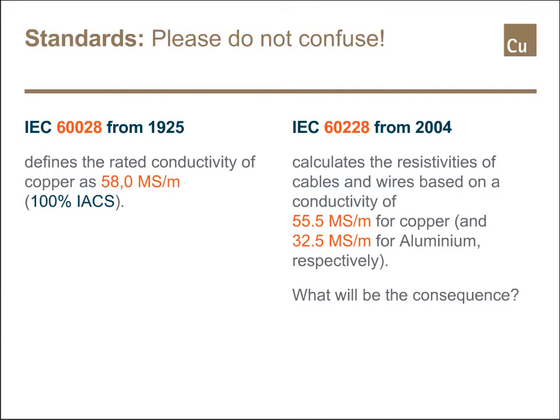That means 1 kilometer of cable of the respective type of cable has a maximum resistance, and these maximum values for each cross-section are calculated with a conductivity of 55.5 megasiemens per meter for copper and 32.5 megasiemens per meter for aluminium conductors. Now, in fact, the conductivity of copper nowadays is 58.0, and then I think you can imagine what the cable manufacturers will do. In fact, a 16 square cable has only 15 square copper in the end, but it serves the same purpose.